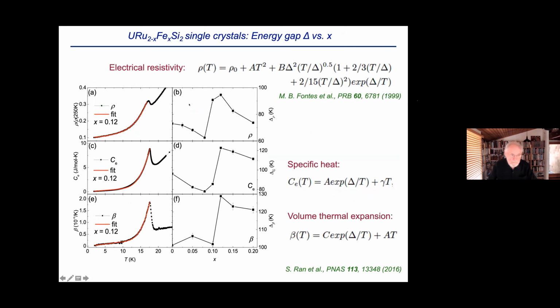And you can also analyze these resistivity, specific heat, and thermal expansion curves. And so basically what we've done is to look at these parts below the transition, which have exponential contributions, which you can then fit to the data and estimate the gap associated with the formation of the hidden order phase. And so from the resistivity, as you increase the iron concentration, you see that the gap decreases and then jumps up and then decreases. And then similarly from the specific heat, you find a similar behavior. And then also from the volume thermal expansion, you also see a similar behavior. And the scale here is very, very close. So this is one piece of information that characterizes the transition from the hidden order phase into the large moment antiferromagnetic phase.